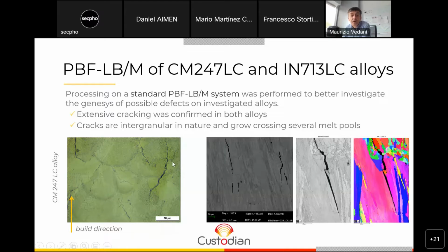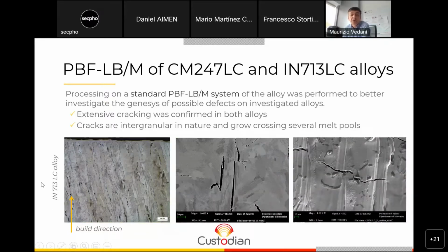The cracks were intergranular in nature, so they run between one crystalline grain and the other, and they could cross several melt pools. Here you can see some reference images for the CM247 LC alloy, while in this slide you can see some similar images of similar cracks for the Inconel 713 LC alloy. So the point was always the same.